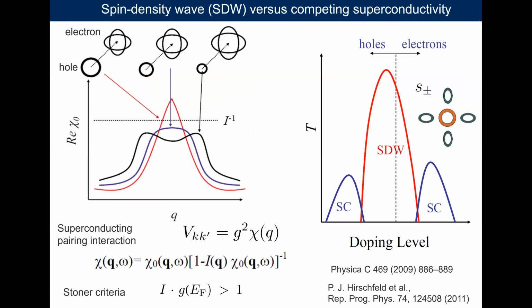Now, in terms of the spin density wave, we have electron and hole pockets, and in many iron-based superconductors, spin fluctuation has been proposed as the mechanism for pairing. That's because here the hole and electron pockets could nest. We have a large density of states, and that could enhance the Lindhard susceptibility.